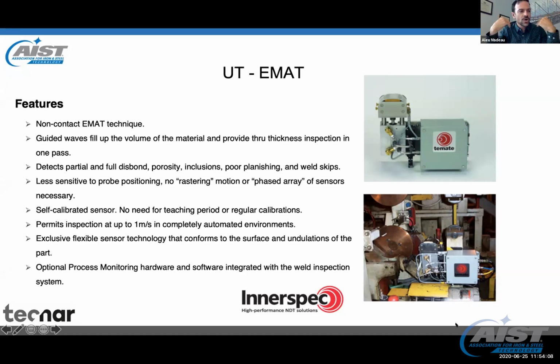In UT, you need to know how much sound you have generated. That can vary a lot depending on surface conditions. So the EMAT actually samples the sound going towards the weld. So when you get the back scattered intensity, you can normalize that with what was sent, and you can have a normalized reading.